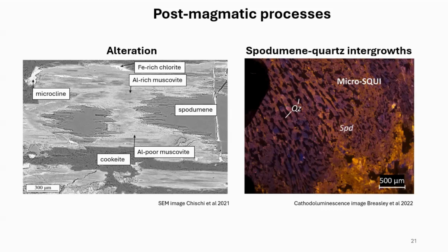This second one, here's a great example. This is some work on Tanco. And there's a texture called SQUI, which is a short form for spodumene-quartz intergrowths. And here, it's not so much a problem like the previous one, where heating it up to 1,000 degrees is going to change things. It's like, no, you look at the scale here, 500 microns. So this micro-texture, Tanco was particularly interested in us working on this.